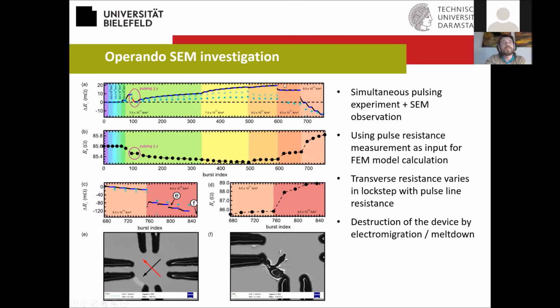These traces here are what we see experimentally for the transverse response. Here is the longitudinal resistance of these pulse lines. We see that our resistance first goes down, and as we increase the current further and further, the resistance eventually goes up again. Now we use our FEM simulation to calculate the transverse response, and we see that it follows pretty nicely the actually observed one. It's not exact, but the qualitative behavior is very close, and these results are semi-quantitative within a factor of 2 or so. Okay, this is very nice.